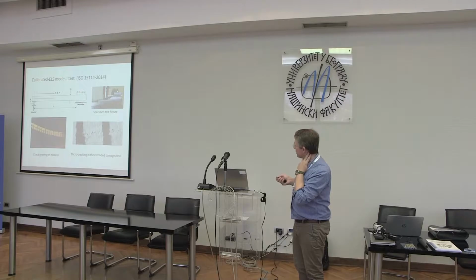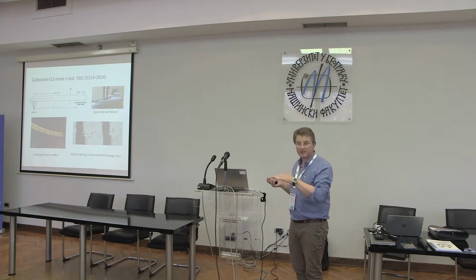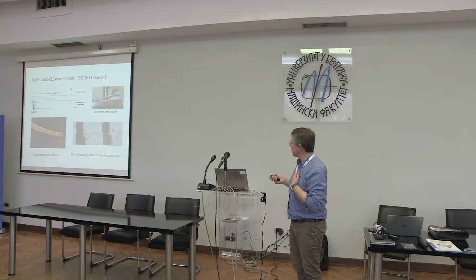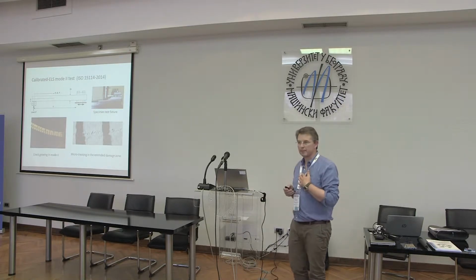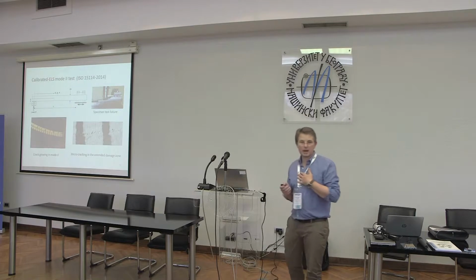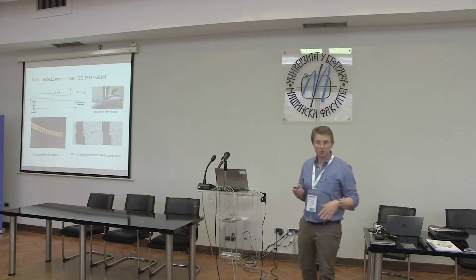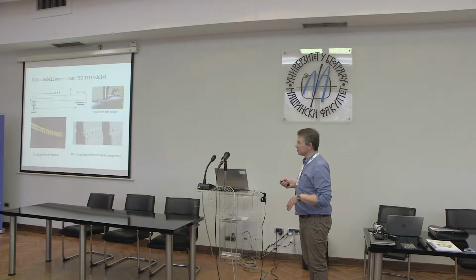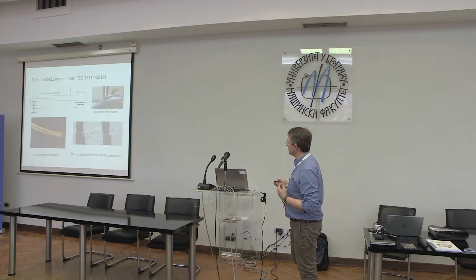But just to explain the basic methodology, we have a specimen which has an embedded defect. This is our inserted PTFE strip in the centre of the specimen at one end. It's put into a clamp and clamped. It's important that the clamp is on a free sliding roller trolley, because otherwise you introduce horizontal forces during the experiment. The experiment only wants vertical forces, so you allow this to slide freely. So this is realised in our lab. This is our free sliding fixture. This is our clamp. This is our loading port here. This connects to the tensile testing machine.